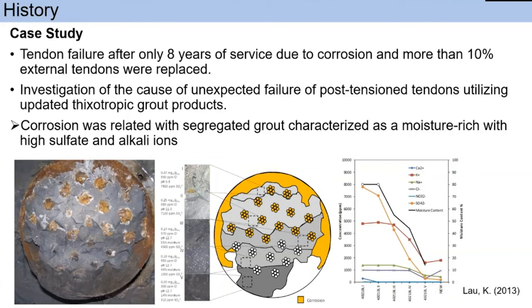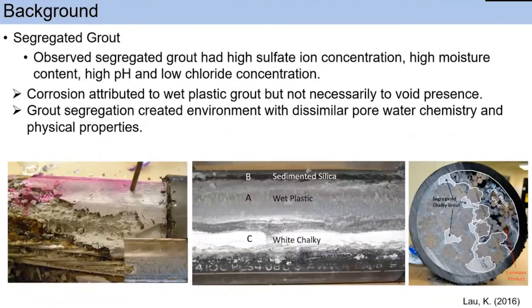Rather, the deficient grout had high moisture content and elevated sulfate concentrations. Strand in the location of the tendon failure exhibited severe corrosion mostly concentrated in the upper portion of the tendon cross-section. In these pictures, you can see the segregation of grout. Grout at high elevation, that is soft grout, had high sulfate ion, low chloride, high moisture content, and high pH. In the first picture we can see wet segregated plastic grout, and this pink color shows a phenolphthalein indicator spread on the grout, and it shows pink color that is an indicator of high pH.